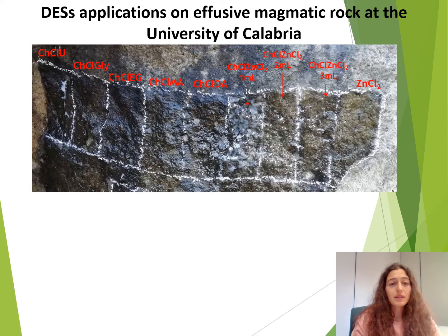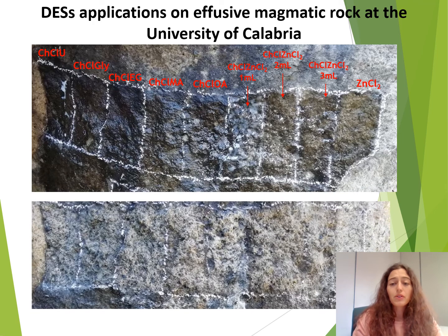All the synthesized deep eutectic solvents were applied with a brush on an effusive magmatic rock at the University of Calabria. After 3 days, the surface layer was removed with a sponge. After application, after 20 days, no biological growth was observed. This work is still in progress and it will need to be analyzed with the digital microscope.